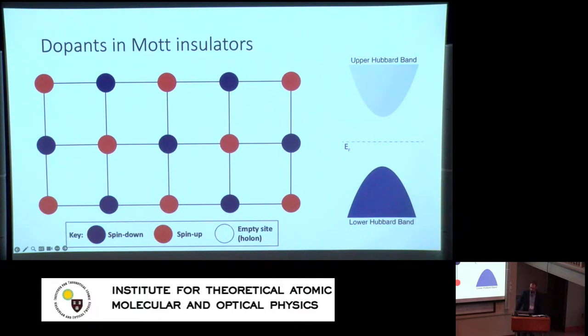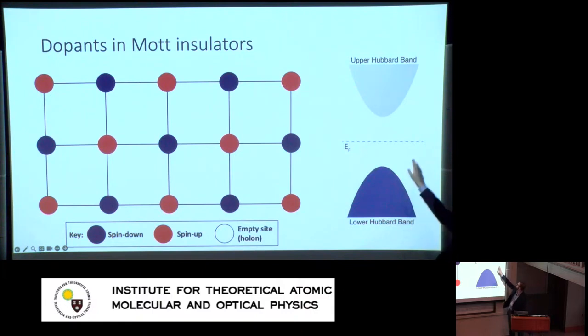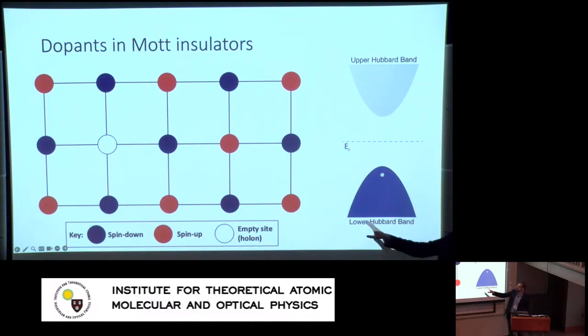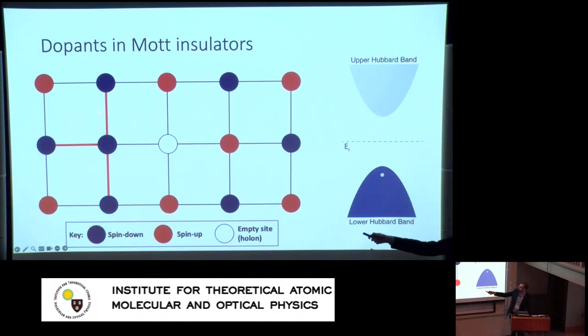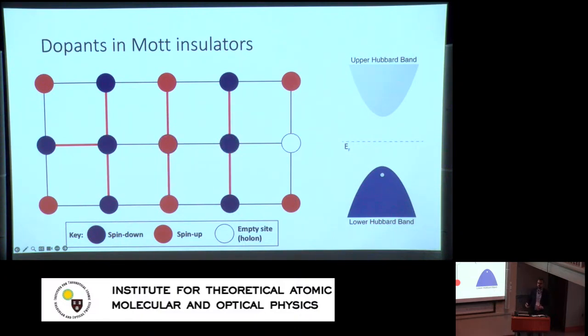If this happens so often in a semiconductor, why doesn't it happen in a Mott insulator? To answer this, we need to consider the differences between photodoping in a Mott insulator versus a semiconductor. I'm specifically discussing two-dimensional spin-1/2 Mott insulators — basically the limit that the cuprates are in. When I hole-dope the system by removing an electron from the lower Hubbard band, spatially this creates a hole in the antiferromagnetic lattice. As this hole hops around, each time it hops it creates a set of spin-flips — leaving in its wake a string of magnetic excitations. So the charge degrees of freedom are inherently coupled to the spin degrees of freedom.